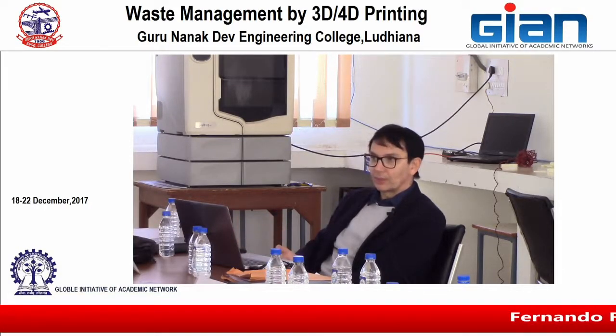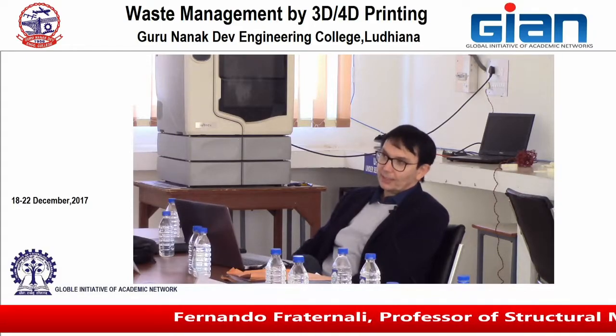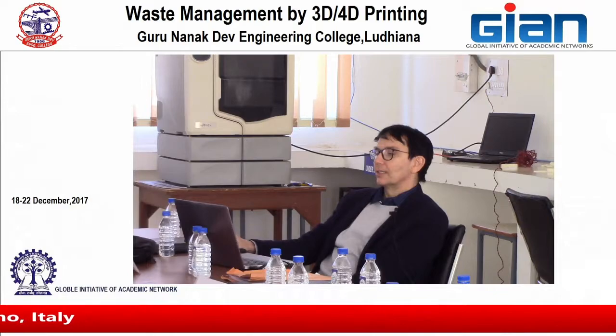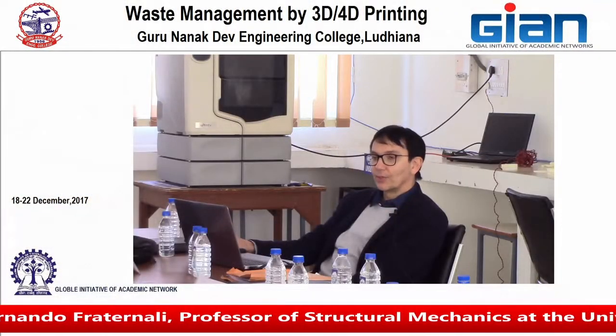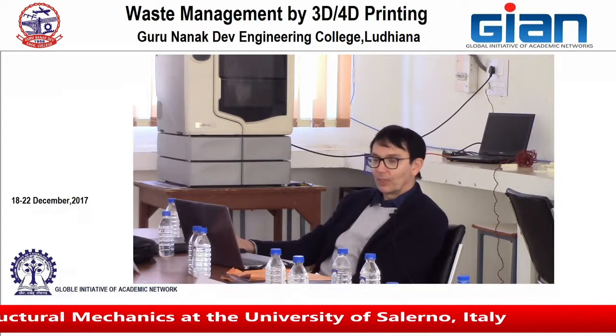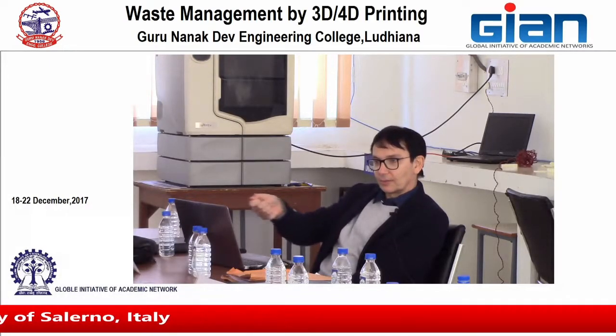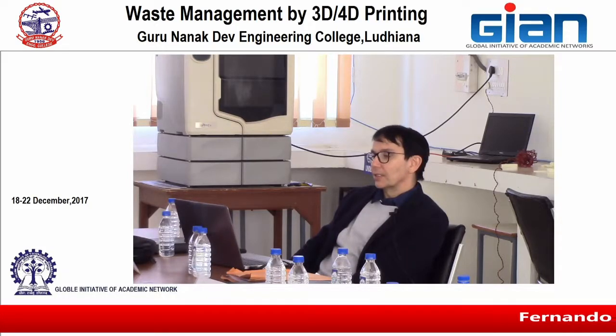This is not a pull-out test. This is a three-point bending test. But still, the fiber works in tension. So you can see that, by comparing this picture with this one, there is more material attached to the fiber in the presence of the embossments. And this is true also in the case where you create a micro pull-out effect, and you have a macro pull-out effect and the micro pull-out effect when the fiber is in place.